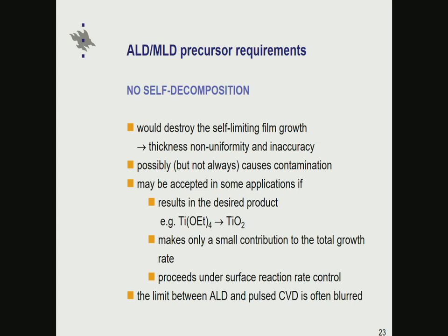Okay, this self-decomposition I already expressed. We can't have that because we want to have self-terminating surface reactions. And if we are losing this requirement, then we start to observe thickness non-uniformity, inaccuracy in controlling the film thicknesses, perhaps conformality, and so on. In general, it's thought that every time there is a decomposition, there are also impurities being incorporated into the films, but that's not necessarily the case.